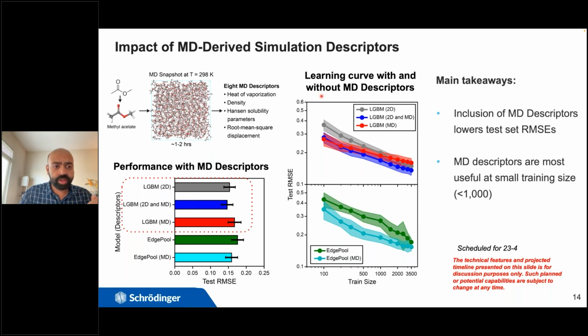For example, here you can see a learning curve. The training set size is increasing as you go along the x-axis. On the left side, we have a low dataset size regime, and on the y-axis, you have the root mean square error. The error is going down, as expected, as we increase the dataset size, because we all know that as you increase the dataset size, the machine learning model performance improves. But what is surprising is that in the low dataset regime, the MD descriptors are actually performing much better than the pure graph-based approach or the pure 2D descriptor approach. And most of our customers are really working with low dataset sizes. So coming up with really powerful physics-based descriptors that can help in the low dataset regime is a really powerful demonstration here.